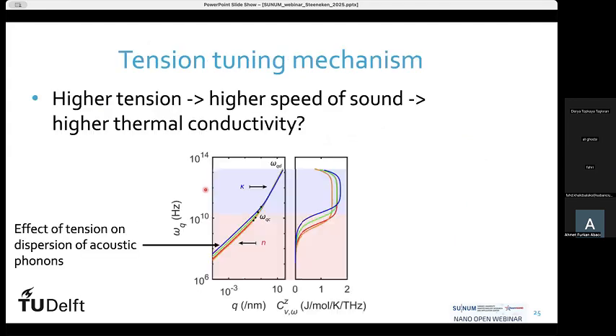However, when we started modeling that in more detail, we saw that indeed the resonance frequency and the speed of sound do depend on the tension, so on how much tension we put. But actually, if you look more into this, at higher frequencies, the speed of the phonons in graphene, so the speed of sound, depends mostly on the bending rigidity kappa and not on the tension N anymore. And actually, most of the heat is transported by lattice vibrations, so phonons, which are in this high frequency regime. So that means that this model that we had could not explain what we saw in the thermal time constant.